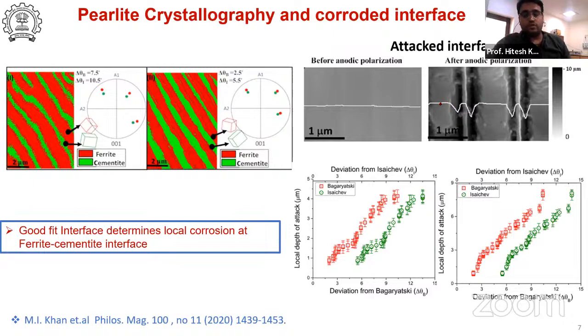What we observed, two things. This is basically galvanic corrosion, not pitting or uniform corrosion. It's galvanic corrosion. One is behaving as an anode, another is behaving as a cathode. We calculated the roughness of the material before polarization and then after polarization. What we observed is that near the interface there is a sudden increase in roughness. You can see the material is more etched out near the interface. So this comes out with the theory.